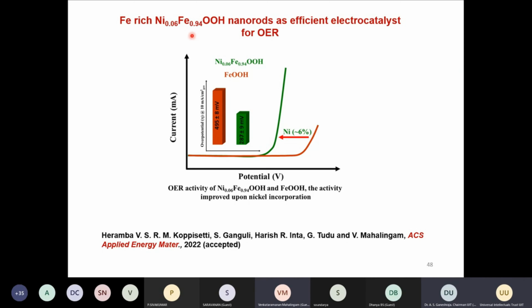So in this context, we were trying to prepare bulk material also, but preparation of oxyhydroxide is not very easy. It's a little challenging. So we tried to prepare this oxyhydroxide as a nanorod. We wanted to make a small structure so that we will have that nickel, even if a small amount, close to the surface so that the activity can be improved. So what we have done is nickel 6%, only 6% nickel on iron oxyhydroxide nanorods.